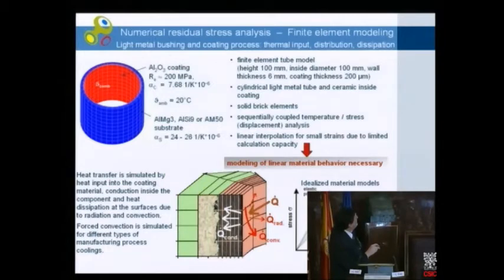And what we have to do first now is to simulate the heat transfer, the heat input into the coating, into the substrate material, and to understand the various phenomena of heat conductivity. So this is the typical setup of the finite element model, and we started to use it with pure elastic properties as a most simple approximation, and there are further approaches to go in more detail with elastic plastic behavior and some further variations. What we have to see is that it is a system of solid brick elements, and we have sequentially coupled the temperature stress fields. And therefore the method is also called coupled temperature stress field analysis.